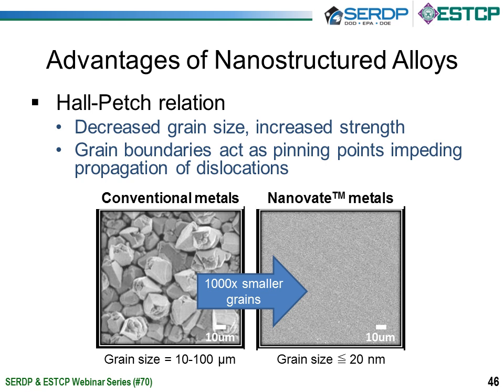So the advantages of nanostructured alloys, John has mentioned those, are governed by the Hall-Petch relation, which describes the increase in strength of metals with decreasing grain size. Effectively, the grain boundaries act as pinning points, so they impede dislocation propagation. This basically hinders the onset of plasticity and increases the yield strength of the material.